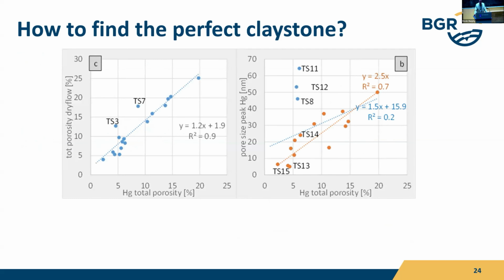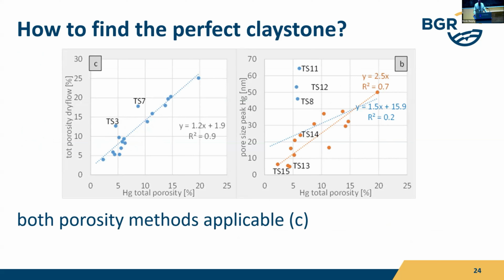First, we started to consider porosity data. We used two methods. The one is the mercury intrusion that was measured by Michael at the ETH. And the other one is based on density measurements with helium and with a dry flow powder, so-called. You can see the results on the left side, and you can see that both methods are in principle applicable, right? So they're quite similar, and we are lucky with that. So we could only use one method, and we're quite sure that the porosity data is kind of significant.